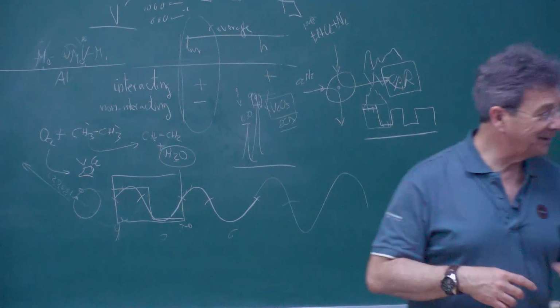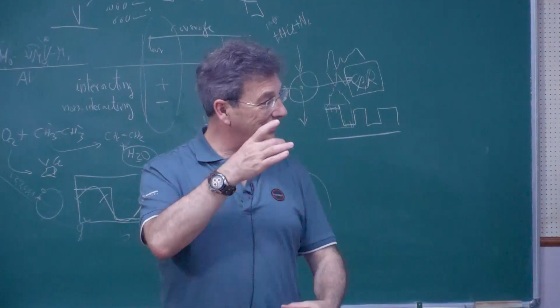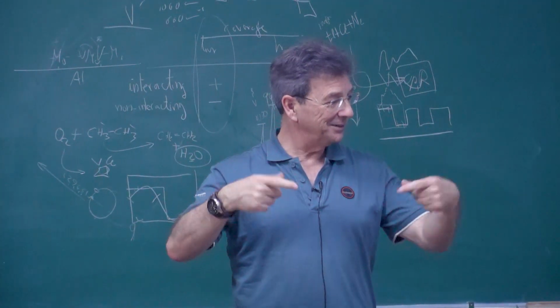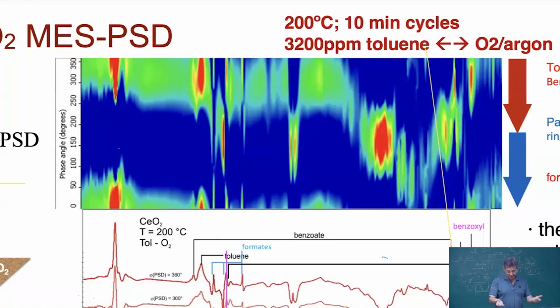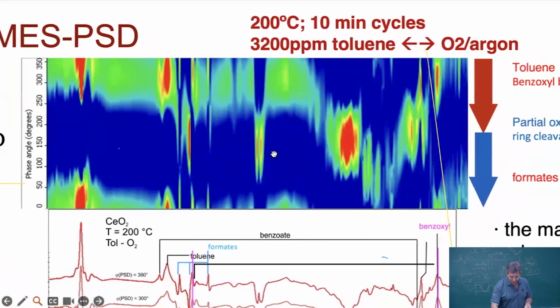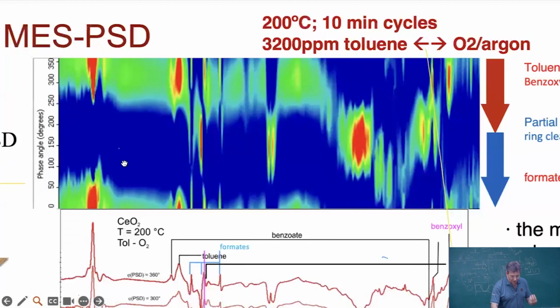Actually, in Madrid they have one of these printed as a roll, and it's like a tube. And I think I spin it like this because it's very nice. But you can imagine, I should have brought it with me or printed it out here. But you can imagine that. So basically you see how this is a completely cyclic process. You see that some bands are formed here when you are feeding toluene. Other bands form here when you are removing the toluene and only air remains. And you can also see this band, this and this band and this band and this band pretty much grow up at the same time and decrease at the same time.